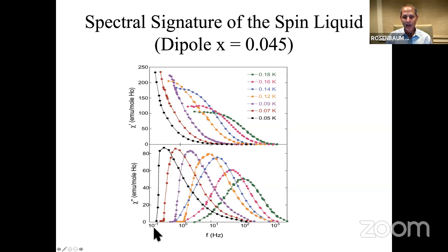And then on the same plot, from 10 to the minus 1 hertz to 10 to the 3 hertz, the imaginary part of the susceptibility. And these contain the same information. They're related by the Kramers-Kronig relationship. But you can see things a little easier on the imaginary part. One thing you note is as you go from high temperature to low temperature, the system slows down, it moves to lower frequency. If this were a spin glass, you would see that this spectrum here, which is about 2 decades wide, so larger than Debye, telling you there's more than one spin doing anything, would broaden out. It would get broader and broader as the spin clusters start to freeze in the spin glass. Here, as you see, it's doing the opposite.